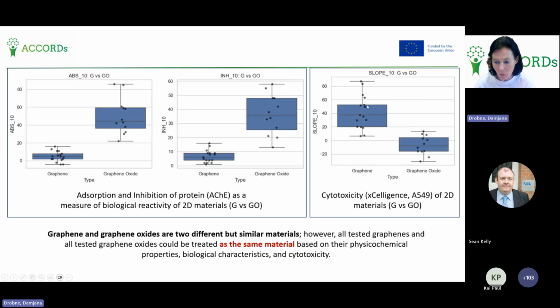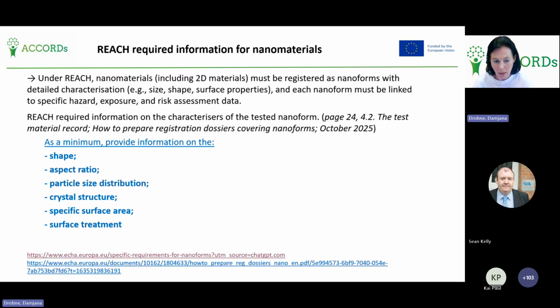And we also link the cytotoxicity to the material characteristics, to the material. And we also see here that graphene and graphene oxide group as different groups. So all graphenes as one group and all graphene oxides as the other group. So they behave as two groups, but within groups there are no differences. So it means that also with this cytotoxicity test, they could be considered as the same group. So we could talk about sameness.